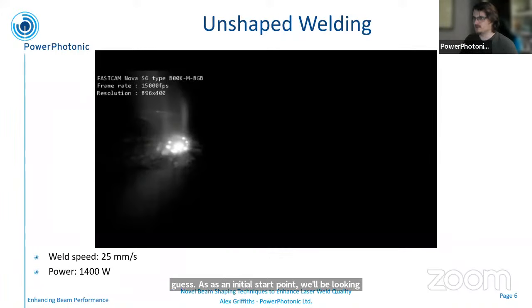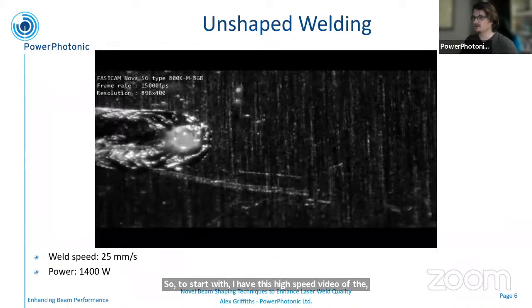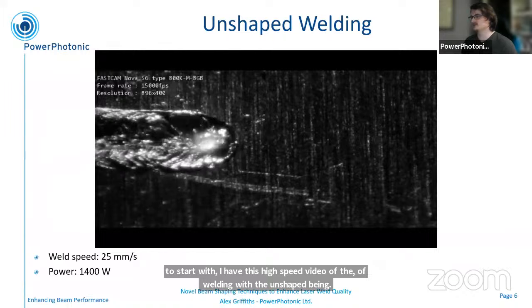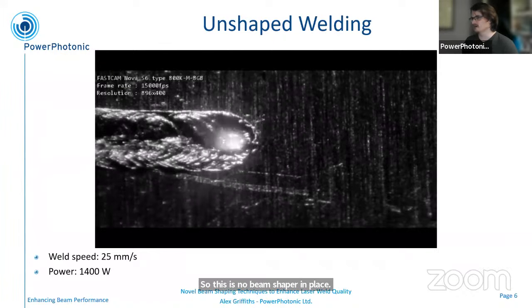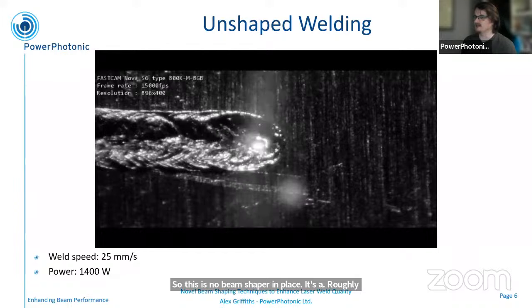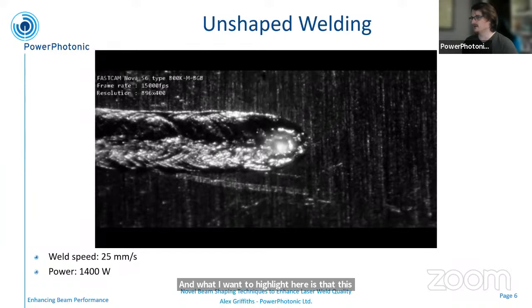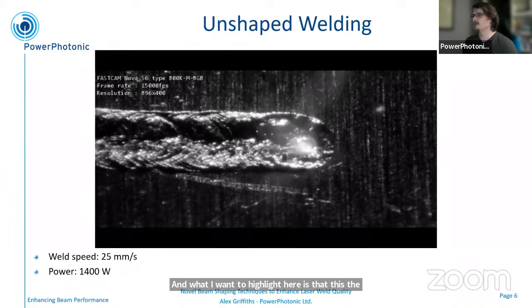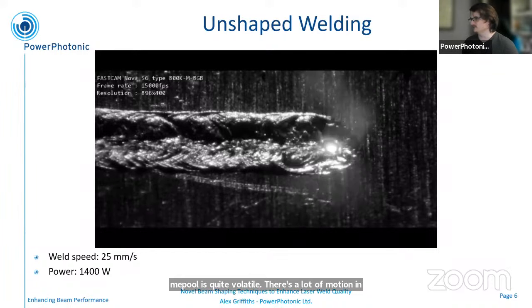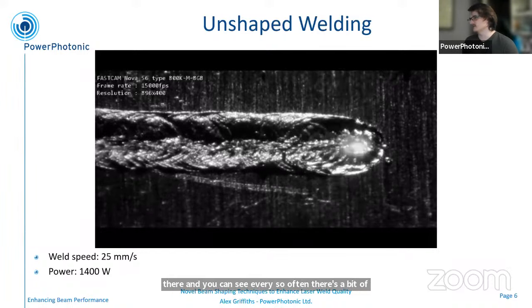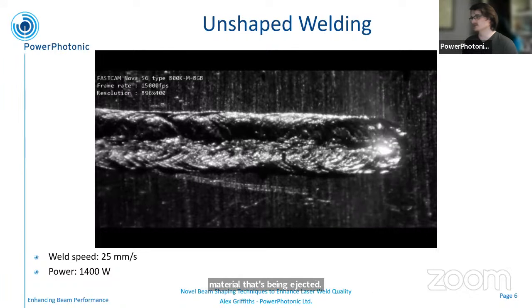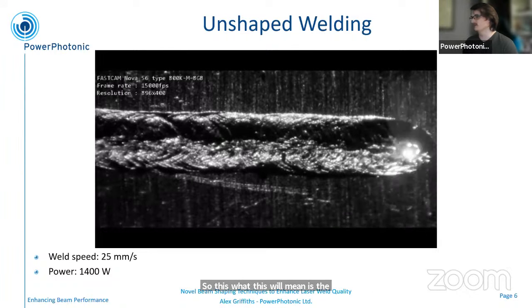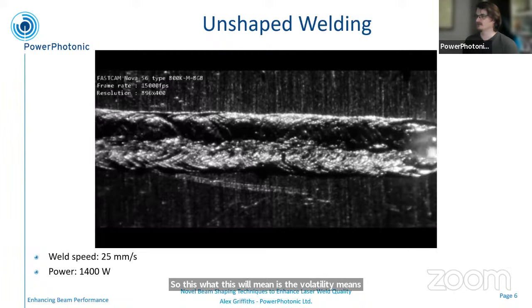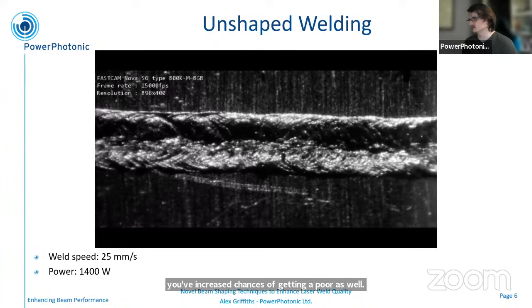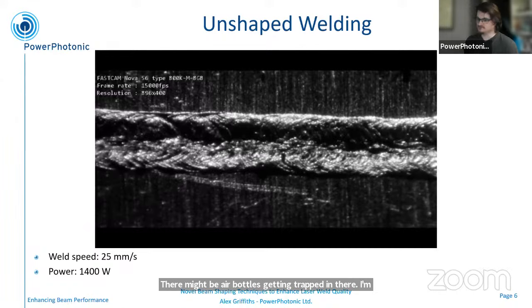So to start with, I have this high-speed video of welding with the unshaped beam. So this is no beam shaper in place. It's a roughly Gaussian profile that's doing the weld. What I want to highlight here is that the melt pool is quite volatile. There's a lot of motion in there, and you can see every so often there's a bit of material that's being ejected. So what this will mean is the volatility means you increase chances of getting a porous weld. There might be air bubbles getting trapped in there. And the ejected material is going to, it's spatter. It's going to end up where you don't want it.